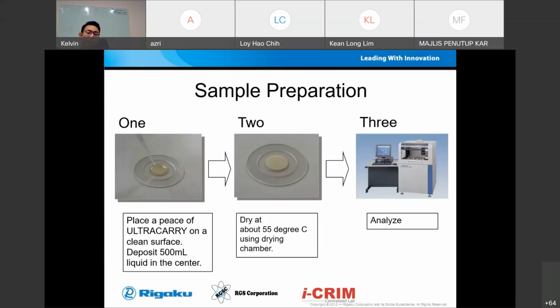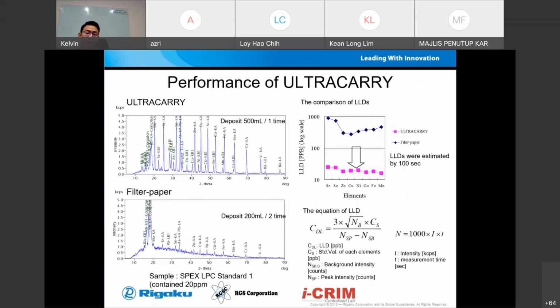For sample preparation, you can drop the liquid sample on here and allow it to dry. You can let it dry outside in the air, or you can use a vacuum drying cabinet to dry it faster. These are the two methods. What we can see here is that with this Ultracarry, the background is significantly reduced and the intensity is significantly higher. The peak-to-background ratio is going to increase. Compared with this filter paper, you have a very huge background, and the intensity is much lower.